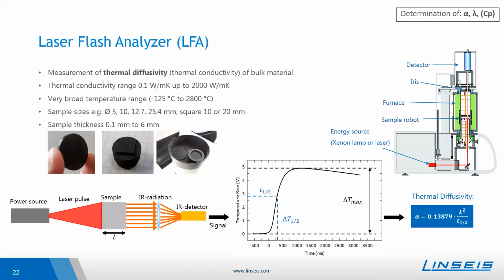So starting with the laser flash analyzer, shortly LFA, it is a measurement instrument according to the ASTM norm E1461, and it measures the thermal diffusivity and also thermal conductivity of typically a bulk material. So with a thickness of, let's say, about 0.1 millimeter to 6 millimeter, the property can be determined. So it allows a broad thermal conductivity range analysis from very low conductive materials to high conductive materials, and the analysis can be performed also in a very broad temperature range, also above the temperature range typically interesting for semiconductors, even to about 2800 degrees Celsius.